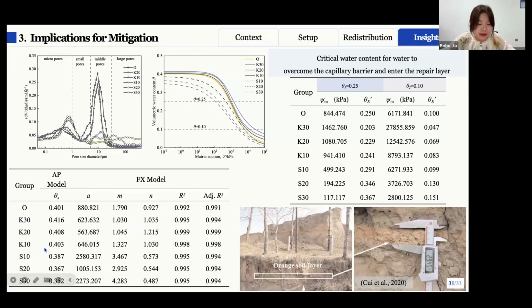For the structure with a fine over coarse structure, when the soil water content is below 0.25, water and salt can still pass through the interface. This means capillary pumping occurs. It may turn into upward migration. In contrast, for the S group, with coarse over fine structures, the critical water content is much higher than 0.25. This means the capillary barrier is most effective, thus limiting the upward movement of the water and the salt.